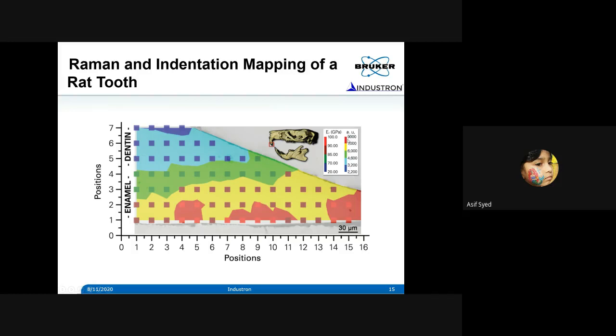I think you are able to see my cursor. You can see that this is for the Raman intensity. It's an arbitrary unit. Higher the intensity means higher the mineral content. The other one that I am showing with my marker right now is the modulus of the material. Okay. So when you look at the enamel material, you can see all the red dots where the mineral content is high. The modulus is also high. The modulus is about 90 GPa. The modulus is very high.